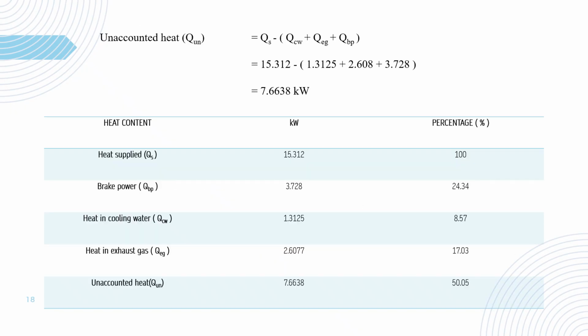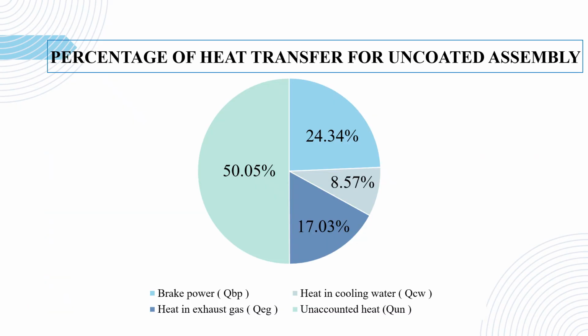Unaccounted heat includes the heat apart from the three, that is brake power, heat in the cooling, and heat in the exhaust gas. So our aim will be to reduce unaccounted heat as much as possible so that maximum heat is retained inside the combustion chamber. As you can see in the table, the supplied heat is 15.312, and from the total heat, the four parts where the heat has gone are calculated, and this is the percentage of the heat transfer for the uncoated piston. So here we have not applied any TBC coating on it, and this is the percentage of the heat flow.